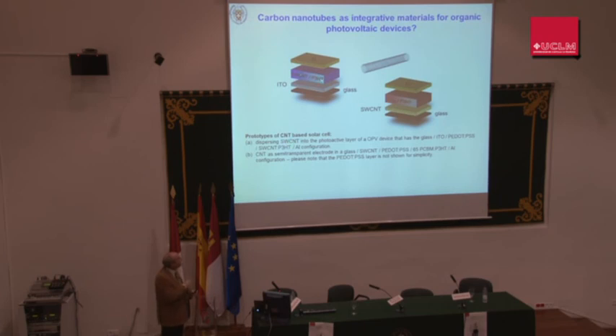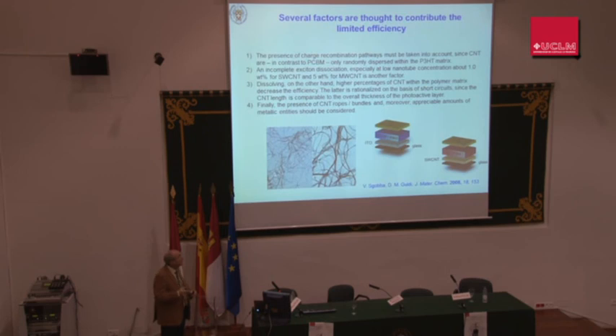In principle, you can consider that they are of interest for the active layer, or to be used, as you can see here, just to favor the charge transfer to the electrodes. These are the 2 possibilities. But in any case, it has been a long time since then. Those papers using carbon nanotubes in the active layer, in general, report very, very poor efficiency. There are many reasons for that, but to date, bulk heterojunction devices have demonstrated relatively poor efficiencies.